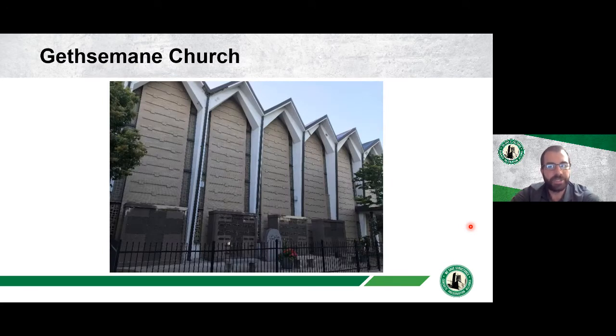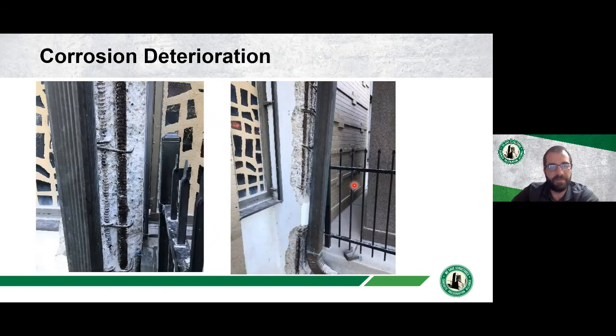This is a church that we did an investigation on. So the roof of the church is supported by these concrete beams and concrete columns. And they were experiencing corrosion deterioration of those columns and beams. As you can see here, you can see that corrosion spalling was occurring of the beams and exposing the rebar, and it was corroding.